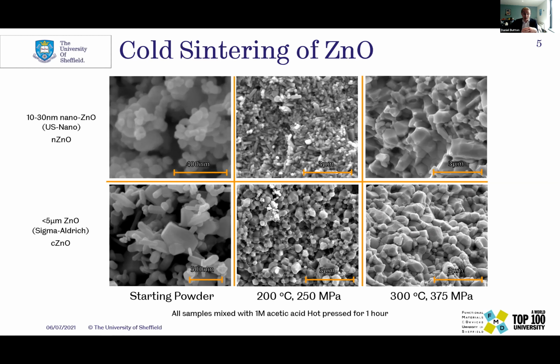As you can see, both with 300 degrees and 375 megapascals achieved a very dense structure that would be typical of a conventionally sintered structure, even though it has a very small grain size. You can also see in the center, with a slightly lower pressure and temperature, there is a very large difference in the shape of the grains. The smaller grains, which showed more grain growth, gave a more columnar structure, which will of course affect the properties, and the larger powder gave a more varied grain size because of the starting powder, less grain growth, but did still densify, and maintained a more spherical grain structure. These are the things we need to look at if we want to start scaling up and controlling this process.